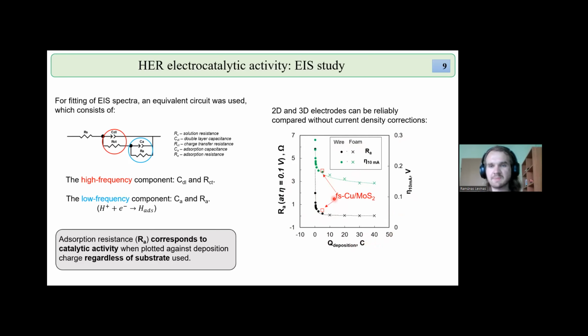And interestingly, well, perhaps not surprisingly, we also find that the femtosecond laser copper molybdenum sulfide film, which was deposited for 5 coulombs, also falls fairly within this range. So regardless of the geometry or the morphology of the electrode, we find that ultimately the overall activity, the charge transfer adsorption resistance, is mostly related to the deposition charge. And this allows us to compare different electrodes without normalizing surface area into milliamps per square centimeter or so on.